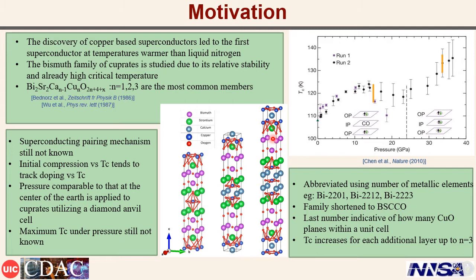Upon compression, Tc tracks the oxygen doping, which is a parameter that is known to dramatically alter the charge carrier concentration within the superconducting planes and therefore Tc. Above a critical pressure, however, all varieties of BSCCO break away from this pressure-induced charge transfer model, and Tc climbs monotonically. The major goal of this study is to see how high we can drive Tc via an external pressure.